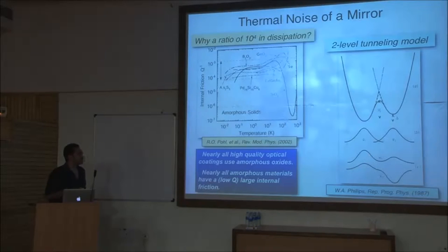And, there's even a model for it dating back to the late 80s, actually, I think even early 80s. And, the model is that in all of these thin films, there's many, many, many two-level systems within the system. And, these two-level systems correspond to absorption peaks up at very high frequency, something like tens, hundreds of megahertz. And, what we see when we do measurements in the acoustic band, which is effectively DC, is we see the tail of these very high frequency resonances. And, so, we're exciting. The two-level system, you may think about it as, you have this whole, long bunch of silica. And, it can be arranged like this, or it can be arranged in a slightly different configuration.